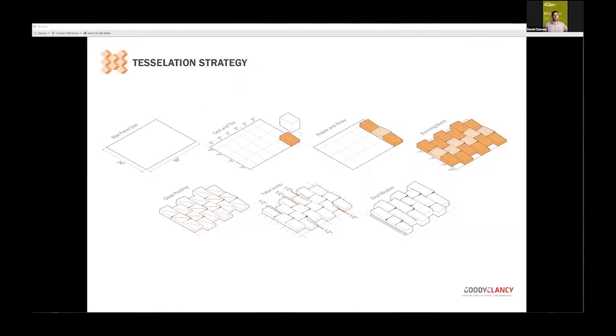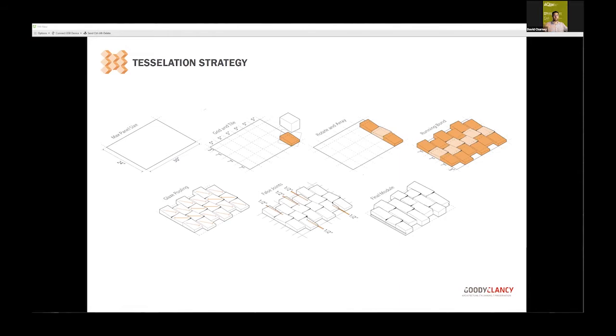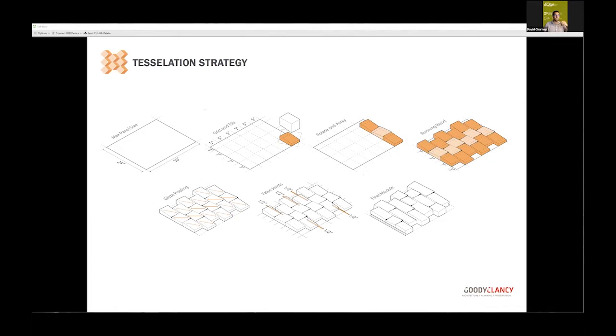Our final model maximizes the ram press at 24 by 30. We slice the face of a standard module so the glaze would pool and run as it's fired in the horizontal position. We rotated it for the running bond pattern, creating a more homogeneous effect. We introduced false joints that come halfway into the panels to hide the seams, and we have our zipper joint between each panel.